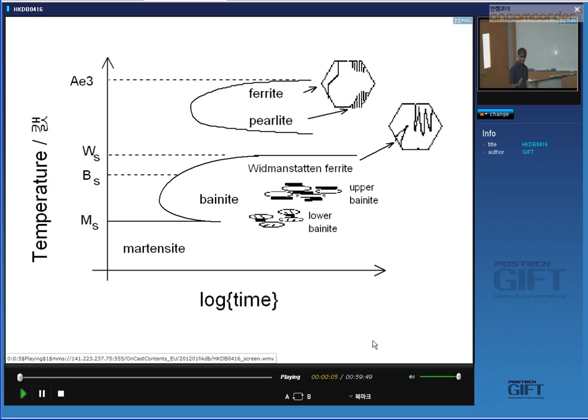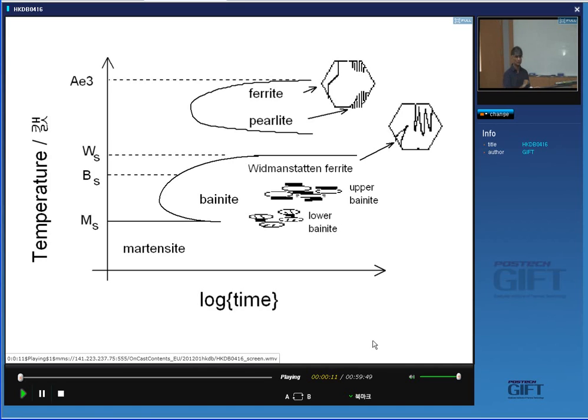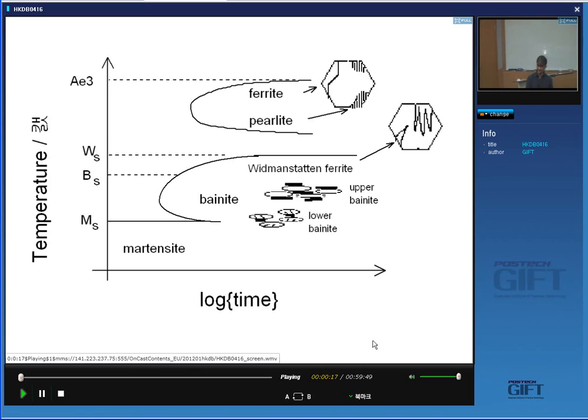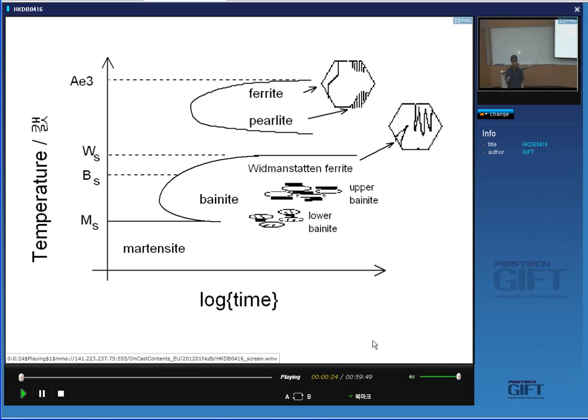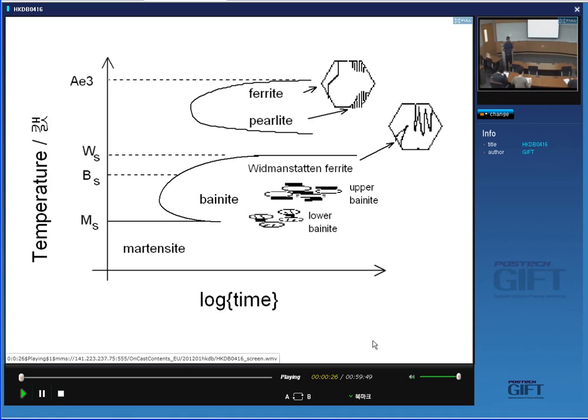Just in case any of you missed, there is a homework assignment which you should hand in tomorrow. It should take you no more than half an hour. Just look at how we derived the growth rate of ferrite from austenite and follow the procedure. Draw a composition profile at the interface and then balance two terms: the rate at which carbon is partitioned or absorbed against the rate at which it is taken away by diffusion.